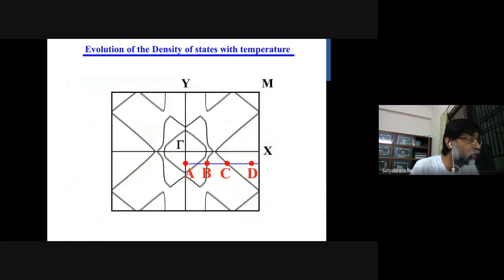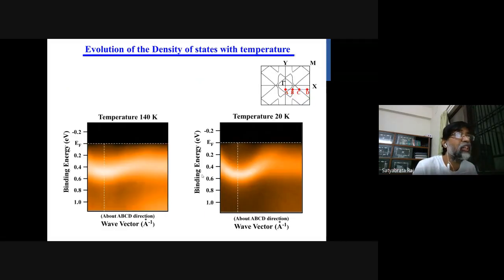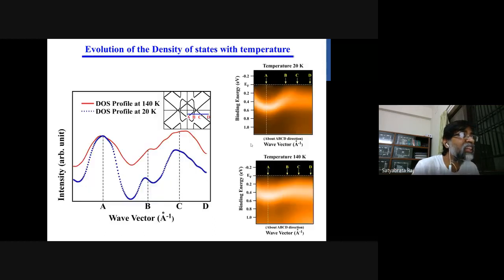So we have taken cuts along this direction to understand the reduction in the density of states. We have taken two band structures and measured their density of states, and you can see at the A, B, C, and D points the red line is 140 Kelvin. At 140 Kelvin you have a similar density of states at all Fermi surface k points,